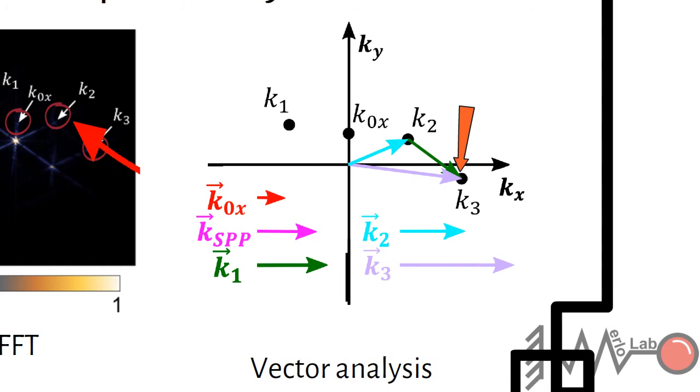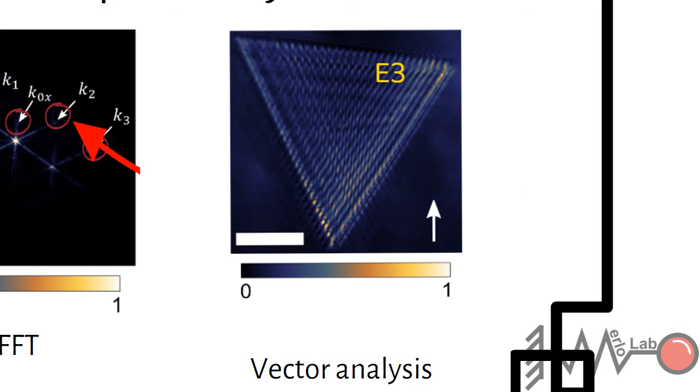In addition, it is important to mention that edge 3 did not generate surface plasmon polaritons, though it scattered the in-plane component of the incident field, as can be observed as a low-frequency modulation generated at edge 3. This could be due to the shape of the crystal and the momentum mismatch on it. Finally, since there was no evidence of far-field components as in the works presented before, we can conclude that the use of apertured probes avoided the generation of the artifacts present in the scattering s-SNOM.